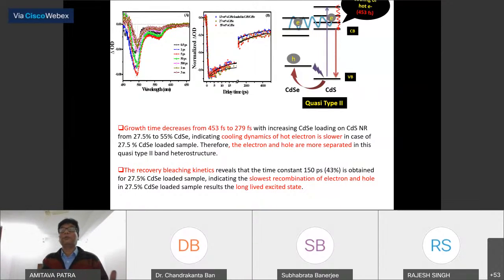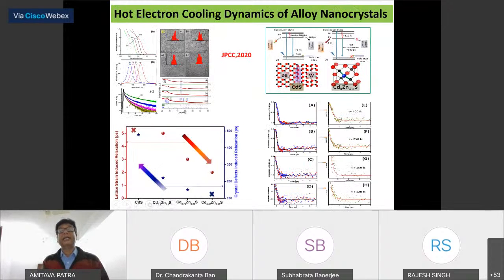All physical chemists are interested. Spectroscopy means only physical chemists want to use it with some molecule. But in material science, you can understand a lot of fundamental, important photophysical processes by using ultrafast spectroscopy. This is one example, an alloy nanocrystal and a pure nanocrystal, because we want to see whether we can control the hot electron carrier cooling dynamics by changing the composition of a nanocrystal. And a very interesting thing is that in solid state you will see different crystal structures, because in cadmium selenide you can tune different kinds of crystal structure, like cubic. Here we have shown that the crystal structure and lattice strain also influence your hot electron cooling dynamics by using ultrafast spectroscopy, and that can be very useful for designing your device materials.